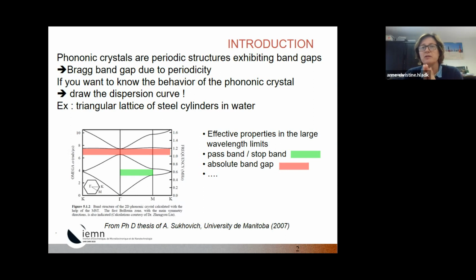So if you want to know the behavior of the phononic crystal, then draw the dispersion curve, like in this case, a triangular lattice of steel cylinders in water. You draw the frequency versus the wave number for different propagation directions. And then from these curves, you can identify the passband and the stop band. It can be a stop band in a given propagation direction, like in the green case, or a stop band for any propagation direction, like in the pink color here. So it is an absolute band gap.